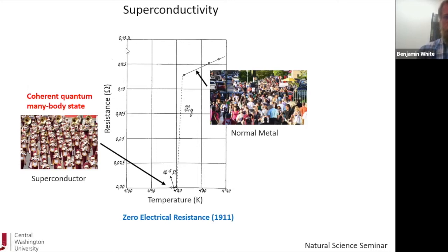so this is the electrical resistance on the y-axis and the temperature on the x-axis, what you'd find is that the resistance gets smaller and smaller as a function of decreasing temperature. So it's getting more and more conductive as you're cooling it down. That's a standard metallic response. And if your material becomes a superconductor, there'll be a particular temperature, depending on what material you're looking at, where the resistance will drop to zero and stay zero, generally all the way down as low as you can measure.